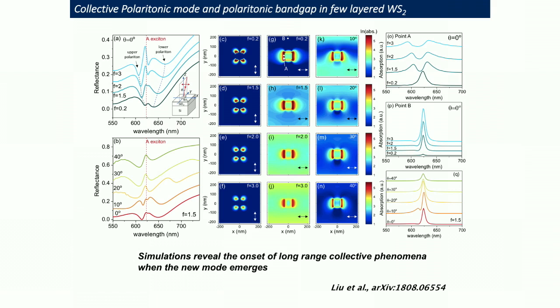So this is basically what was happening. We create a lattice of these plasmons. This is a particle that we have. We put two excitons. One exciton we put in very close vicinity of this particle, so it is in the very strong plasmonic field limit of this particle. Then we put another exciton which is far away, so it does not see the very strong surface plasmon of this particle. So when we have a monolayer, these two excitons see very different fields.